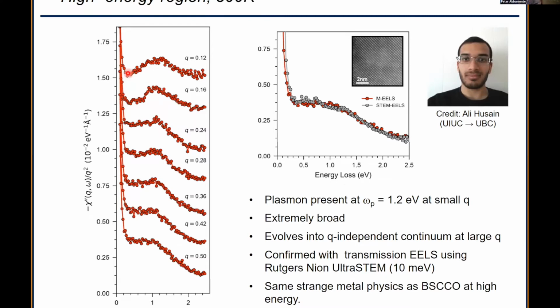At very low momentum, there is a plasmon. It's very broad. The frequency is a little higher than it is in the cuprates, about 1.2 eV. Some of that broadness is because it's measured at finite wave vector. It's sharper if you measure it in optics. But what happens as a function of momentum is it evolves into a frequency independent continuum. And this has all the same scaling properties as the continuum in BSCCO. It's essentially momentum independent over most of reciprocal space, and it's frequency independent up to some cutoff beyond which it just decays like 1 over omega squared.